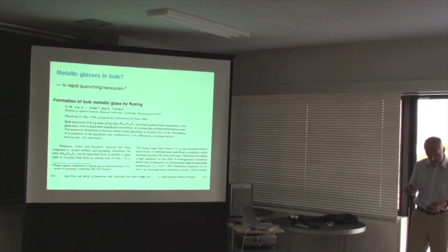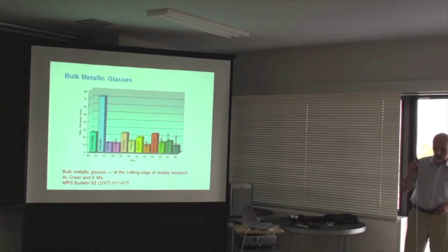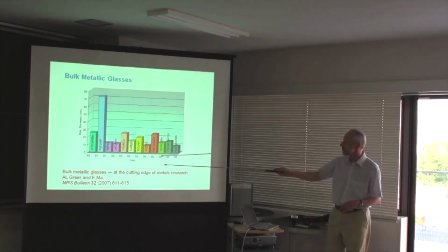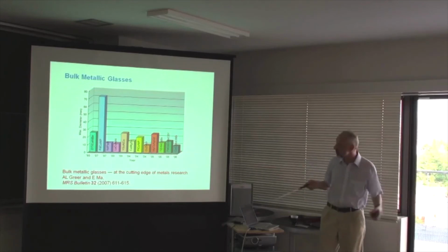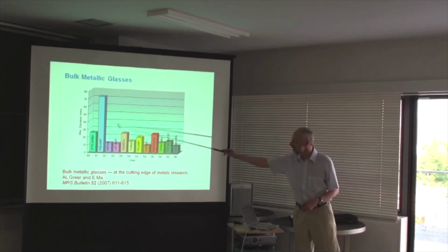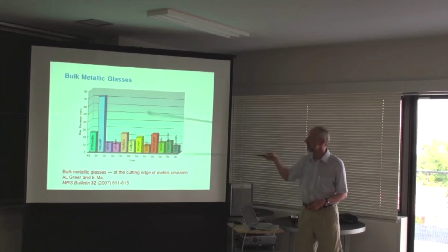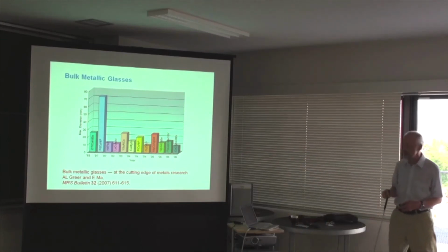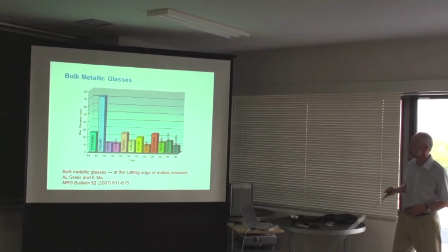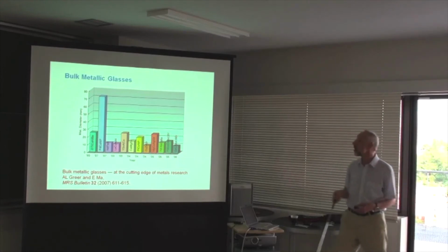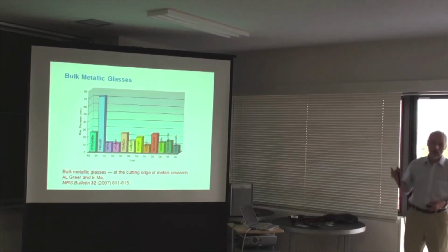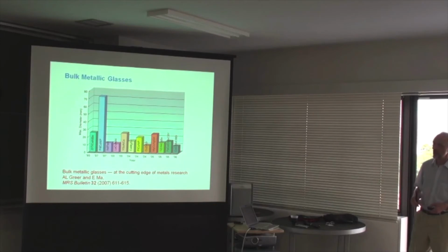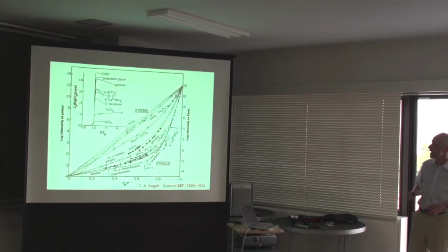And since then, largely through work here in Sendai, the world of so-called bulk metallic glasses has blossomed, and you can get much larger dimensions, over 7 centimeters diameter rods in different compositions and a very wide range of compositions. So that again helps to say that these are real glassy materials that fit in the broader family.